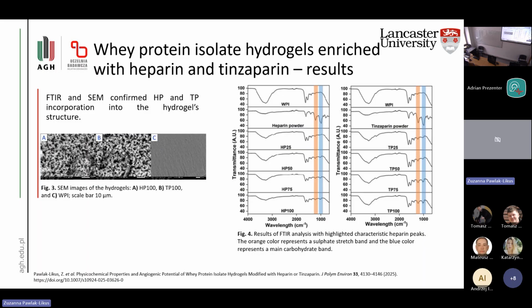And on the right, we have figure 4 that shows FTIR analysis with highlighted characteristic heparin peaks. And we can see that with a higher amount of additives, those peaks are getting more visible. So both FTIR and SEM confirmed that HP and TP were successfully incorporated into the hydrogel structure.